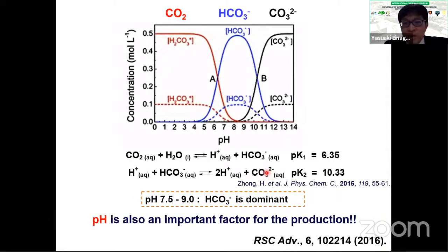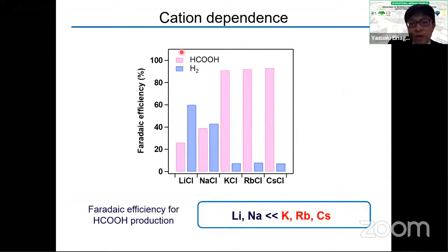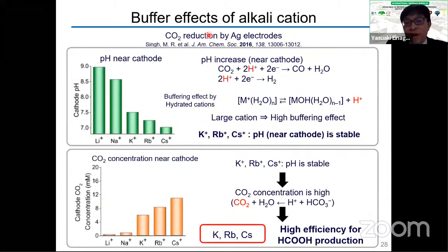Today I don't have enough time, but we studied the fundamentals very carefully, the pH dependence or something like that. And pH is also important. Anyway, by using the copper-modified BDD, we produce methanol. Okay, another direction is to control by electrolyte. First, we change the cation like lithium, sodium, potassium, rubidium, cesium. As you can see, in the case of cesium, rubidium, potassium, we could obtain formic acid, but in the sodium and lithium case, the formic acid decreases. This is too bad, but this is due to the buffer effect of the alkali cation.